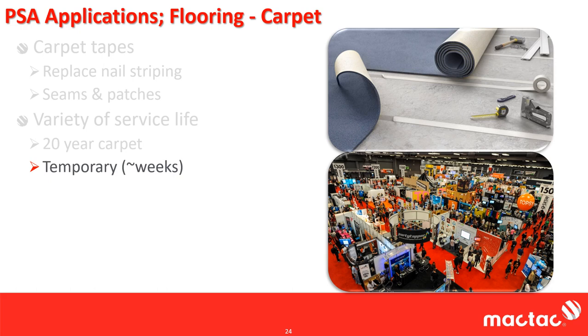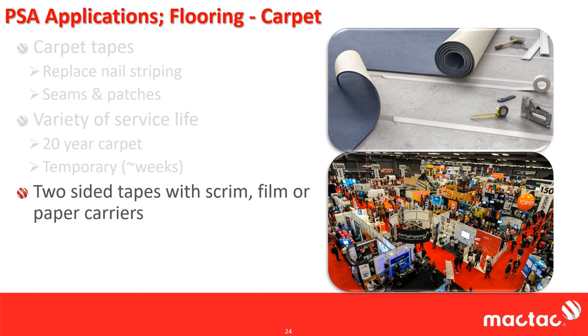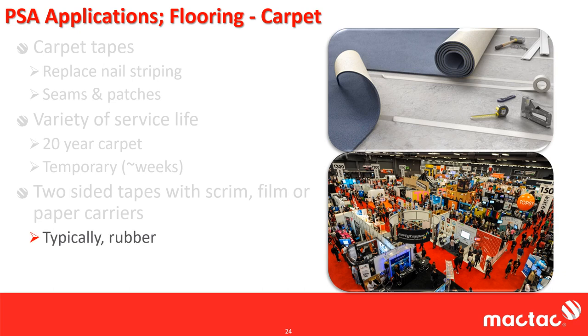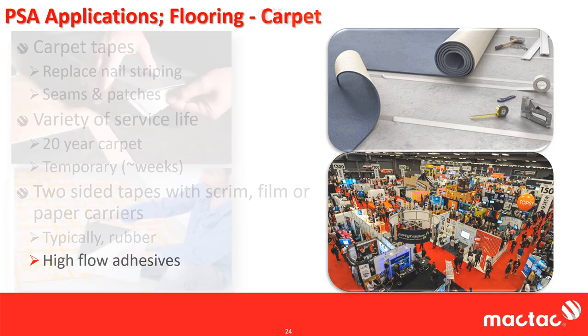A good example of this is trade shows. All that carpet gets taped down to prevent it from lifting and causing a tripping hazard. 3-4 days later, it's all peeled up and reused again. These tapes are double-sided and can use a variety of carriers such as films, papers, or scrims. They are typically rubber-based because of the high coat thicknesses that are available for rubber-based adhesives, and thus offer high flowability to wet out the subfloor underneath and the textured carpet backside.